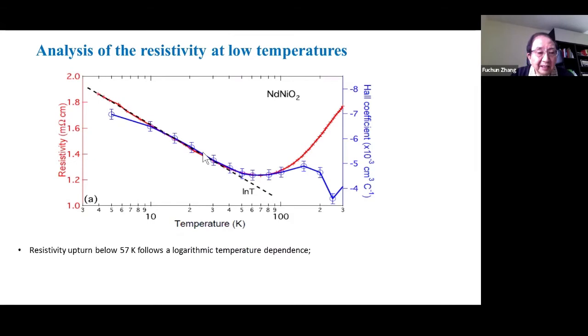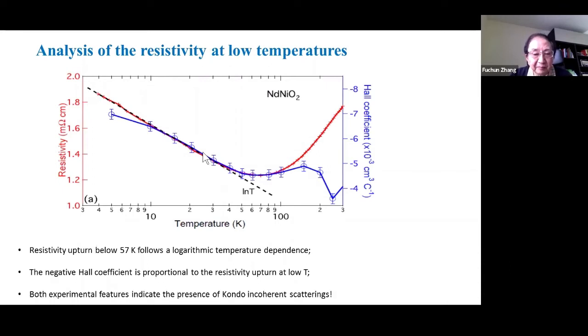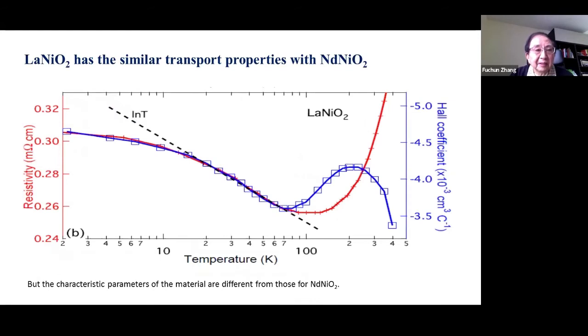And there's also a negative Hall coefficient. It's similar. The lanthanum nickel O2 actually shows similar transport properties in the resistivity, and also fits quite well by log T in this temperature regime. At a much lower energy, there's some deviation from the log T behavior, which we do not understand completely.